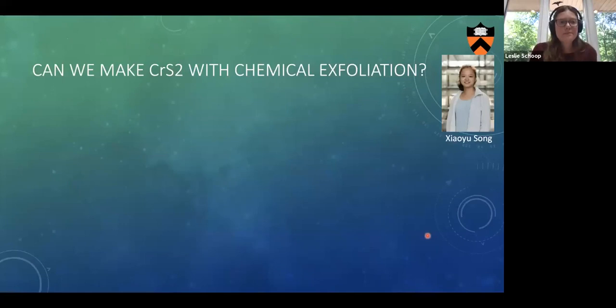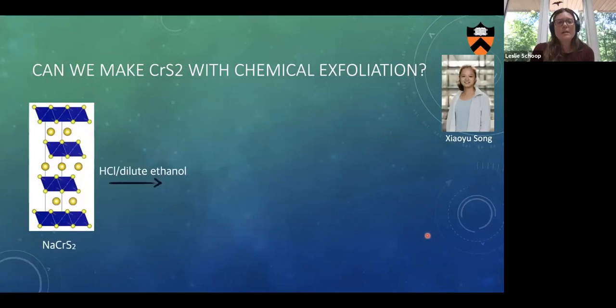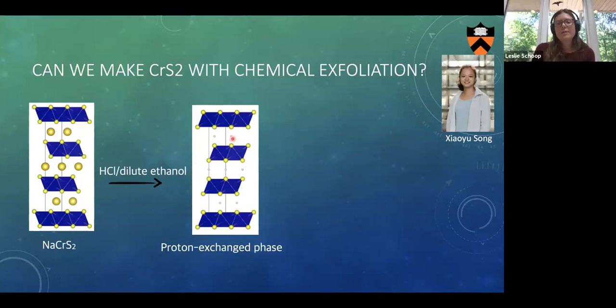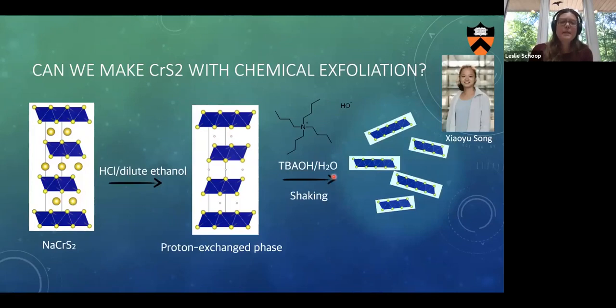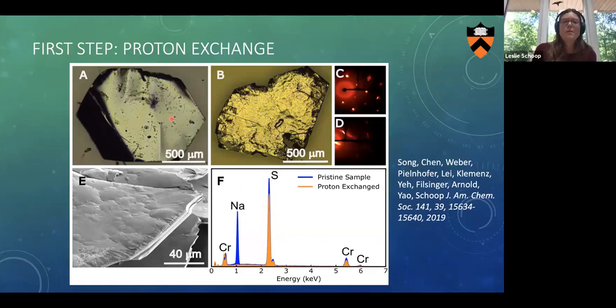And so basically what she was going to try is, can I mix this material with a dilute acid and some solvent and exchange the sodiums with hydrogen atoms, which is very commonly done in oxides. And then use a large organic base and some acid-base chemistry to our advantage to delaminate the system. And so she tried that. This is how it looked first. So she grew a beautiful crystal of this material. She put it in acid. The crystal is still intact. It just doesn't look as nice anymore.